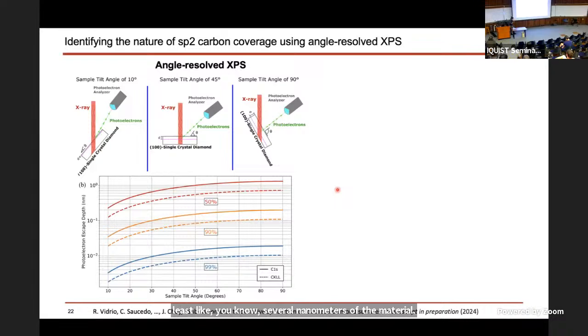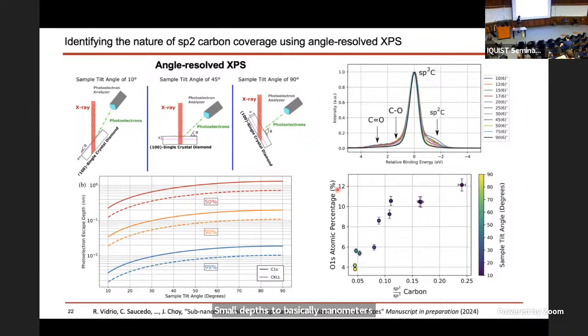So our solution to this, in collaboration with Bob Hamer's group, is to do an angle resolved XPS. What that allows you to do is, as you change the angle where you're exciting, of the X-ray beam that's hitting the sample, you get to probe different depths. And this is a plot of the photoelectron escape probability as a function of sample tilt angle, which shows that as your angle becomes more and more shallow, you get to really probe small depths, to basically some nanometers. And so we've done this, and we show that as you change the angle, you see more and more of the oxygen functionalization and the graphitic carbon, and you have a nice correlation between the amount of oxygen that you're measuring and the amount of graphitic carbon.